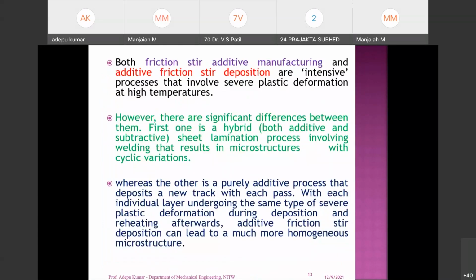Let's come back to this slide. However, there are significant differences between them. The first one is a hybrid, both additive and subtractive process. Sheet lamination processes involve welding that results in microstructure with cyclic variation, whereas the other is a purely additive process that deposits a new track with each pass, with each individual layer undergoing the same severe plastic deformation during deposition and reheating afterwards. Additive friction stir deposition can lead to a much more homogeneous microstructure.